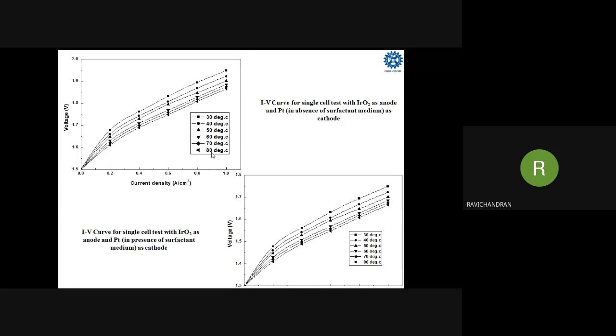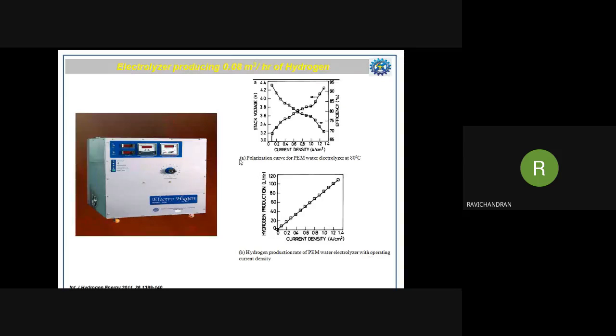As I told you, if we raise the temperature, we can also reduce the overvoltage. At 80 degrees it is 1.8 volt, versus 30 degrees, almost 2 volt. So temperature also plays a major role, as I told you previously. Based on that, we assembled a small cell for our hydrogen generation in our lab. In our lab, we are not buying hydrogen from vendors or gas in cylinders. For our chemical reactions, we generate hydrogen ourselves, with 80 liters per hour capacity.